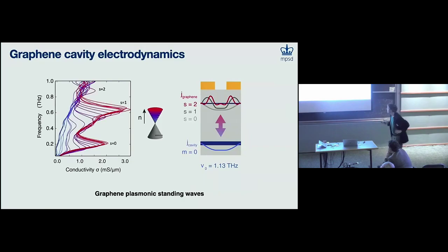Okay, but now what's interesting is when we gate the Fermi level, increase the carrier density in the graphene, we start to see all of these resonances show up on top of this background. And you'll notice two things. So first, obviously these are going to be graphene plasmonic standing waves. So that's what we're seeing here. And so you see a few things with these resonances. One, as you increase the carrier density going from blue to red, the spectral weight increases, which makes sense, and they are also blue shifting to higher frequency.